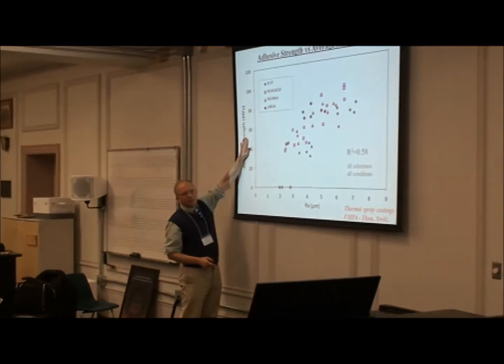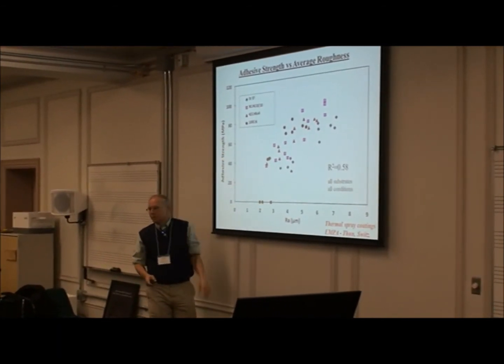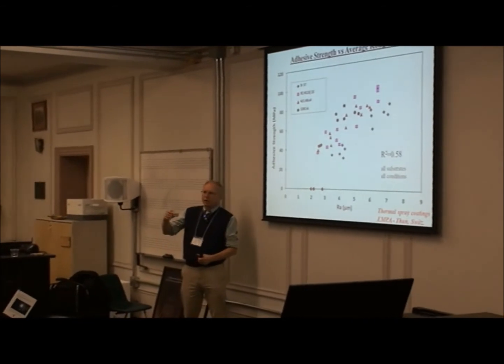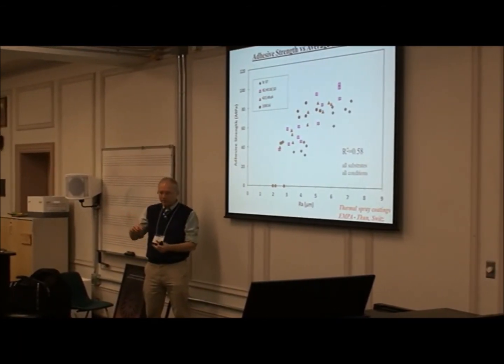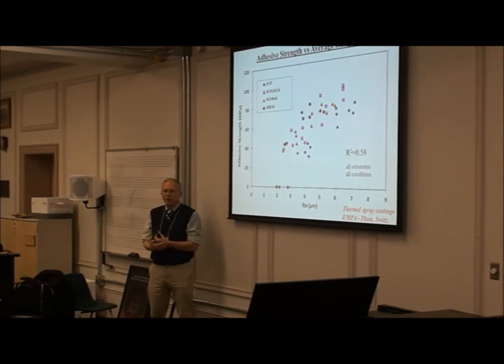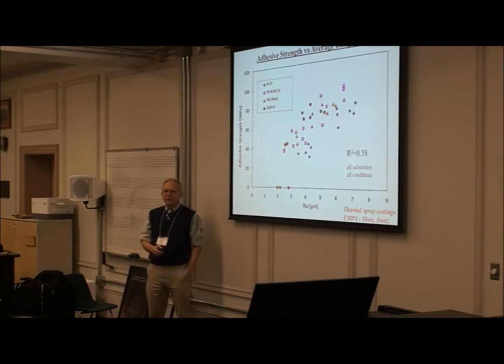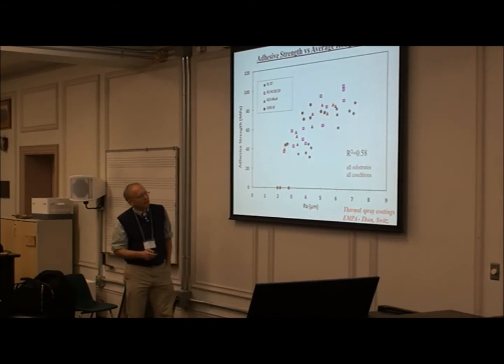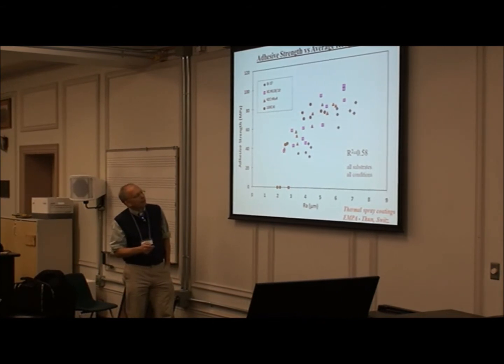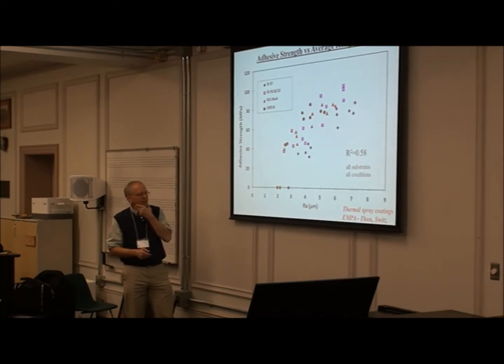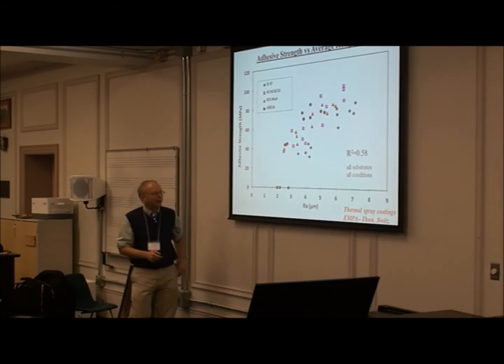Now, the whole thing here, what adds value, is when we can take a parameter that gives us some function. Like we want to have good adhesion, because thermal spray is used, for example, as a thermal barrier coating on turbine blades. And we don't want the thermal barrier coating coming off, right? Because this would be bad for the morale of the passengers in the airplane if this happens, right? And so then the Ra, the average roughness, what happens here? Well, the adhesion was so bad that it fell off, so that's why it has zero adhesive strength. And I should have put the line on here. I'm sorry, I didn't put the line on. You put a line on there and you calculate the regression coefficient, and it's 0.58. So 58% of the variation in adhesive strength is explained by the variation in Ra. All right, so that's not so bad, perhaps.